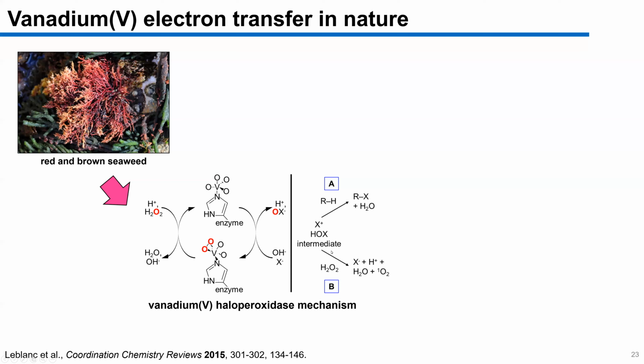And then on the right are the byproducts of the enzyme cycling, where that halide is combined with the hydrogen peroxide to promote the vanadium conformational change, which results in the formation of a hypohalous acid. In this B pathway, it results in the formation of that singlet oxygen radical species that we identified in our system. And then in terms of the degradation of a nearby organic compound, that's this A pathway here. So that hypohalous intermediate can attack a nearby organic compound to oxidize it and degrade the biofilm that's trying to form on the seaweed nearby. But if you incorporate more hydrogen peroxide in this B pathway, you do form the singlet oxygen reactive species.